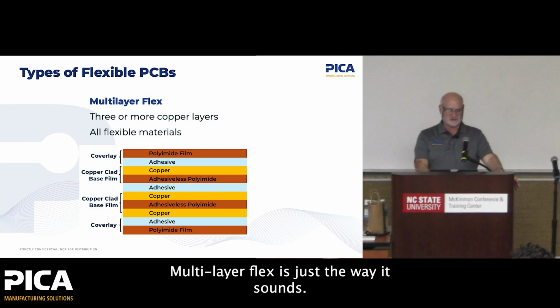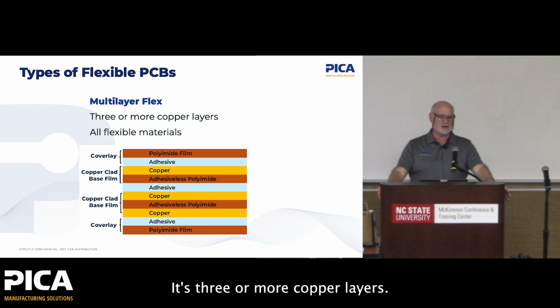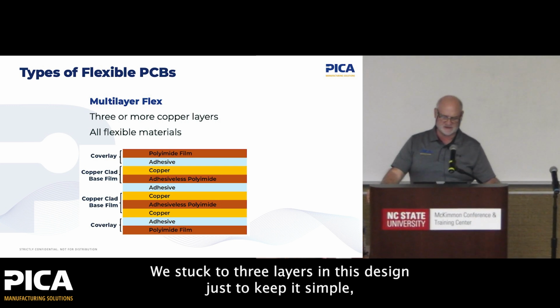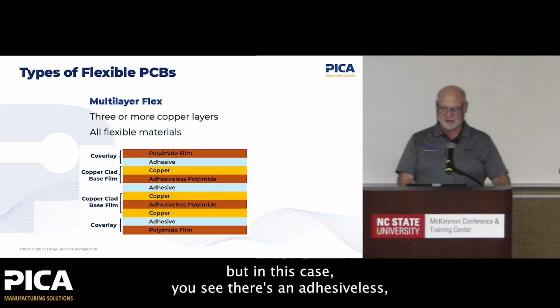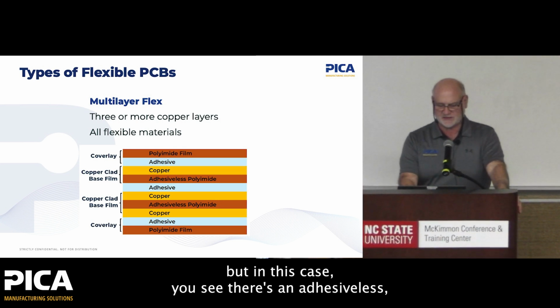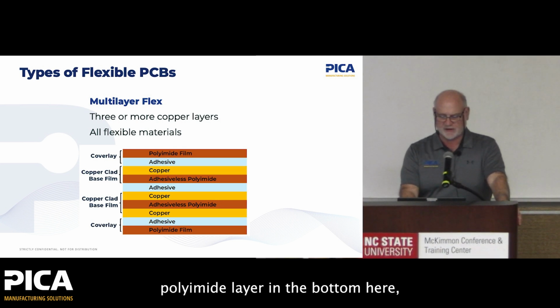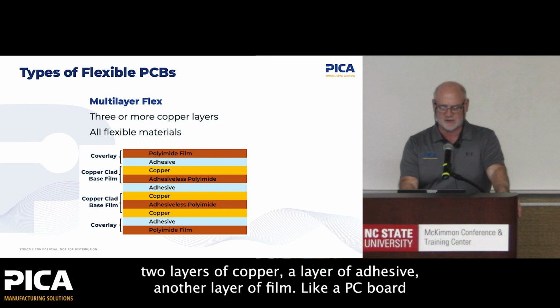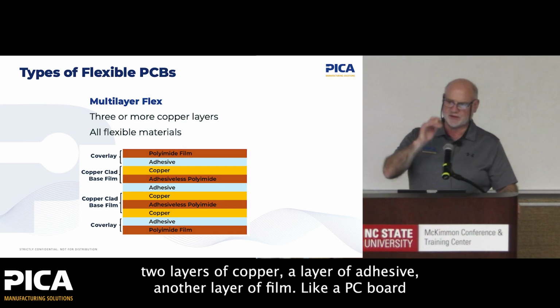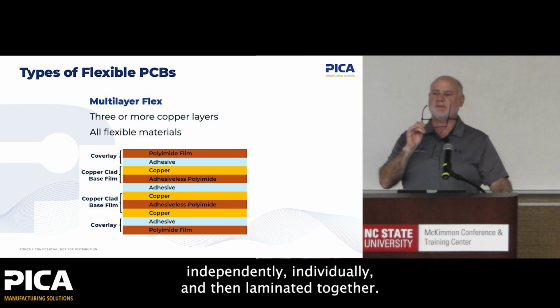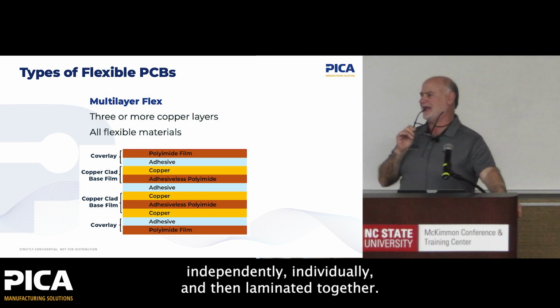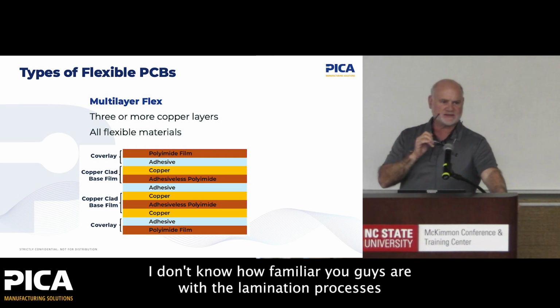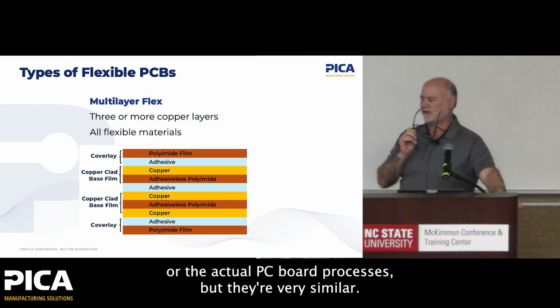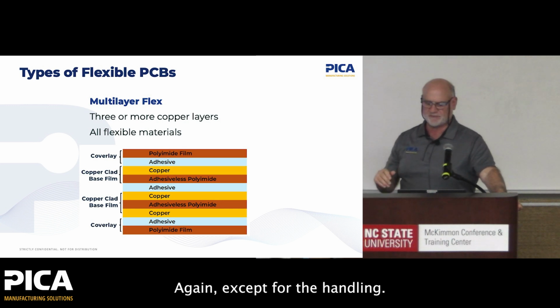Multilayer flex is just the way it sounds. It's 3 or more copper layers. We stuck to 3 layers in this design just to keep it simple. But in this case, you see there's an adhesiveless polyimide layer in the bottom here, 2 layers of copper, a layer of adhesive, another layer of film. Like a PC board, these layers would be processed independently, individually, and then laminated together. I don't know how familiar you guys are with lamination processes or the actual PC board processes, but they're very similar, again, except for the handling.